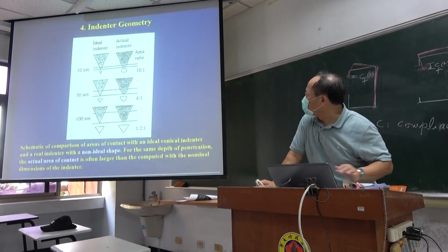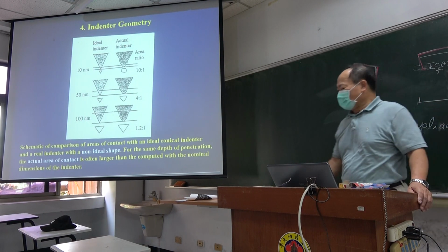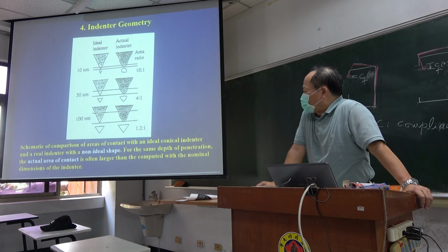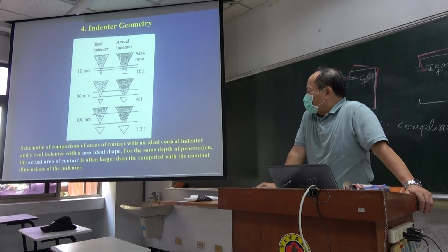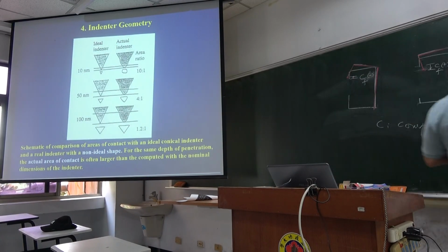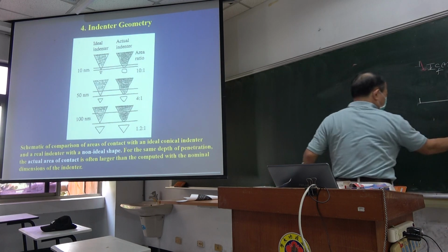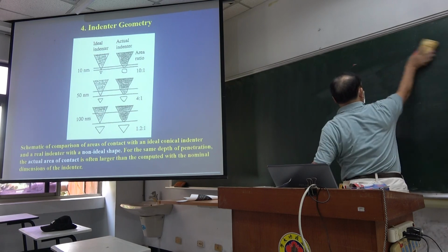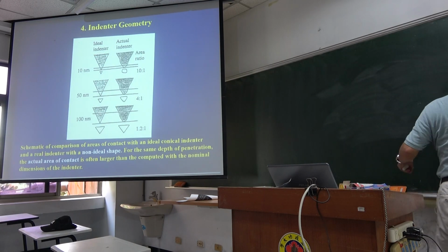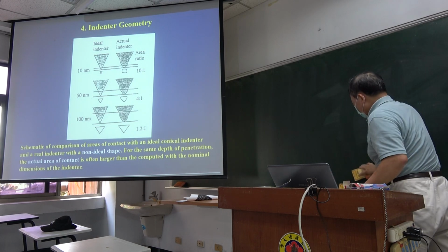This is the third term. The fourth term, we call the indenter geometry. What's indenter geometry? This is a very important factor in our indentation test in general. Here, in general, we want to use the indentation test to measure the hardness or Young's modulus of the thin film, not the substrate. Because the substrate, in general, is easy to obtain from your handbook or any resource.